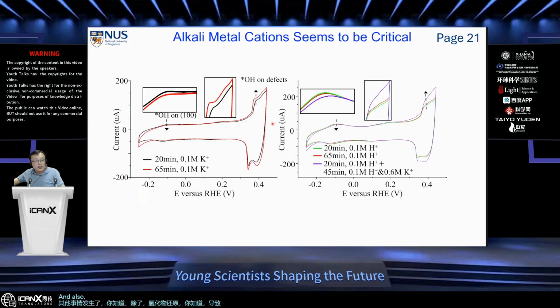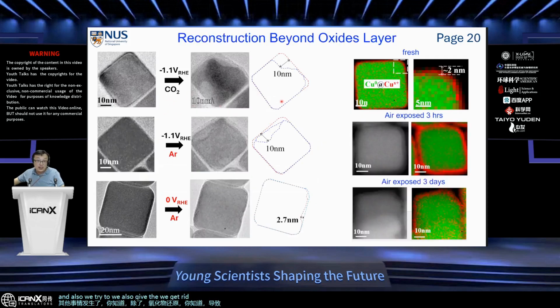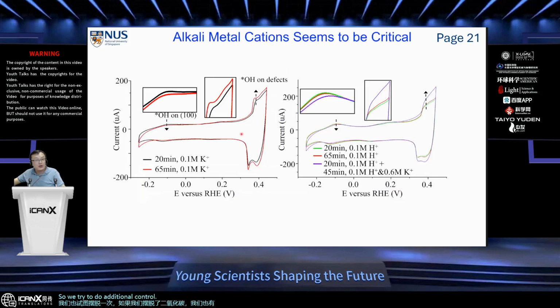And if we get rid of the CO2, it also happens as well. So we try to do an additional control experiment. In this case, we use CV in addition to the TEM, because CV samples the entirety of the catalyst, while the microscopy only looks at a small part. So by using the two, they complement each other and give us more confidence in our conclusion. And you can see here, the copper cubes give very nice signals at certain potentials, representing the OH groups on the (100) surface, or OH groups on the defect sites.